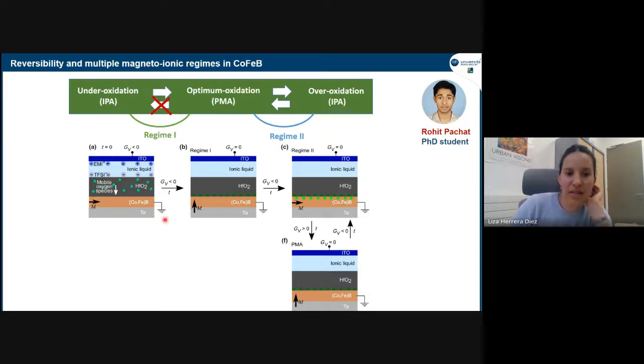So if we start from a system that hardly has any oxygen at the interface between the cobalt-iron-boron and the oxide, then it is likely that we have binding sites for oxygen that are non-equivalent. We have some binding sites that are extremely favorable and low energy and decrease the energy of the system. And then that oxygen would probably bind preferentially in those states because there's no oxygen anywhere. So there will be a first wave of oxygen that would bind into these more favorable sites. And then if we keep adding oxygen, the oxygen would just go somewhere else, in interstitial sites or maybe more into the layer.